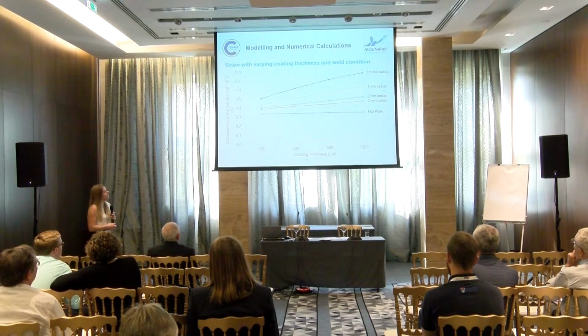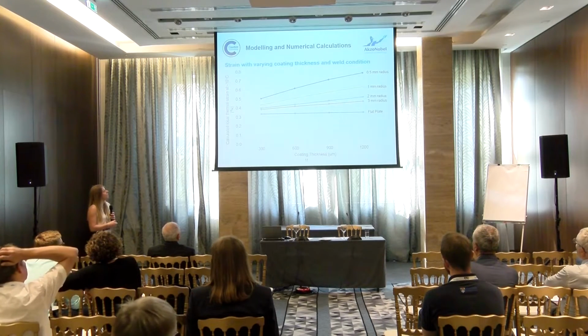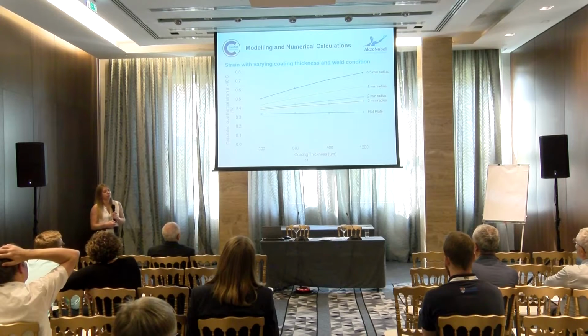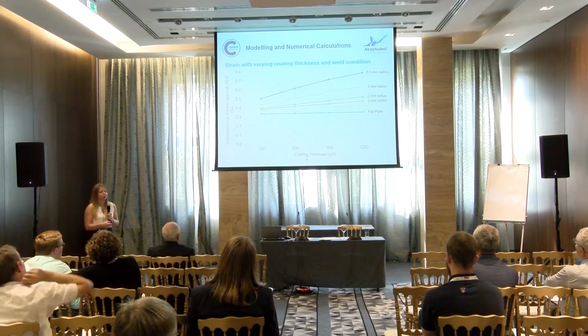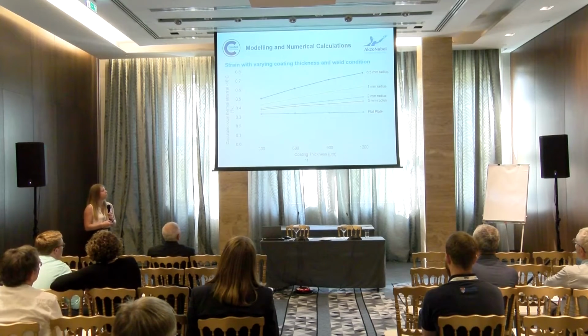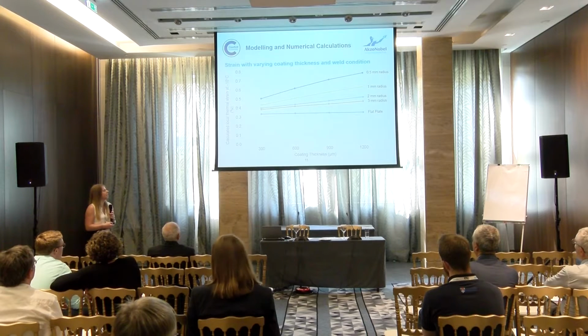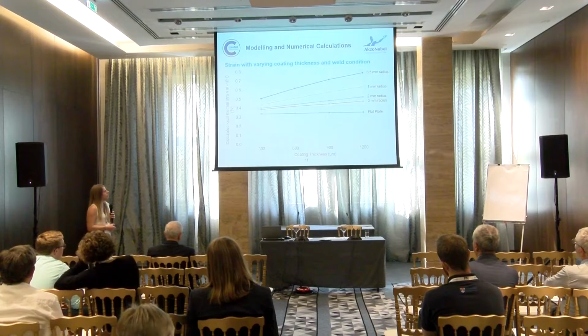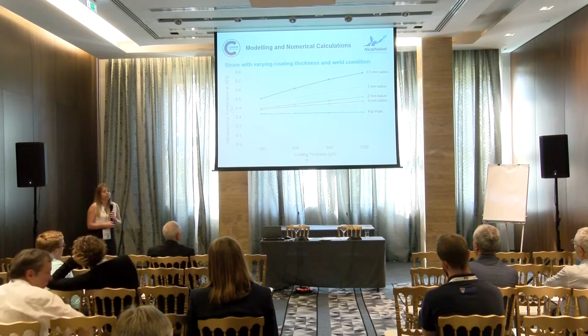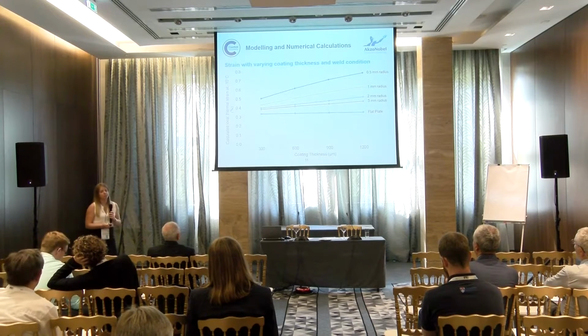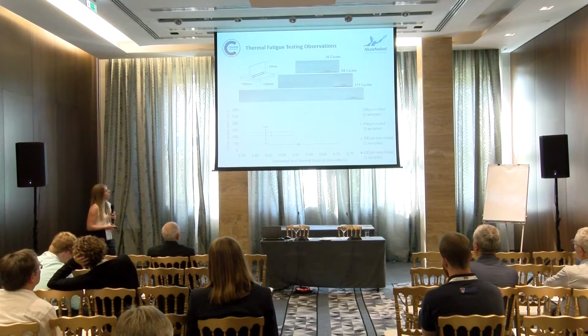So each of the individual models produced the following results for thermal strain at -10. It is very clear to see that as coating thickness is increased, there will be an increase in thermal strain within the weld fillet region, and a reduction in weld fillet radius size will result in further increases of thermal strains. So the condition that will produce the highest level of strains is a thick coating applied to a very small weld fillet radius. But also on the flat plate area, there was no change in internal strain, so it is completely independent of dry film thickness.